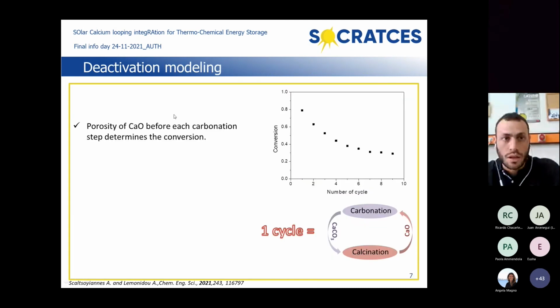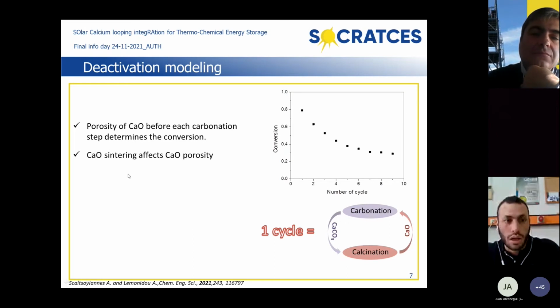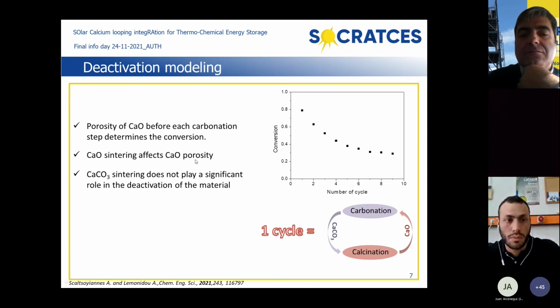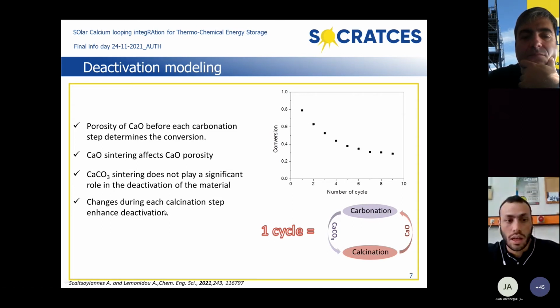So the last part is the deactivation modeling, as I said. Here you can see a typical conversion versus number of cycles curve for limestone. As you see, it loses more than 60% of the initial absorption capacity after 10 cycles. From our study, we concluded that the porosity of calcium oxide before each carbonation determines the conversion of the material. Also, that calcium oxide sintering affects calcium oxide porosity, while calcium carbonate sintering does not play a significant role in the deactivation of the material. And finally, that changes happening during each calcination step enhance the deactivation.